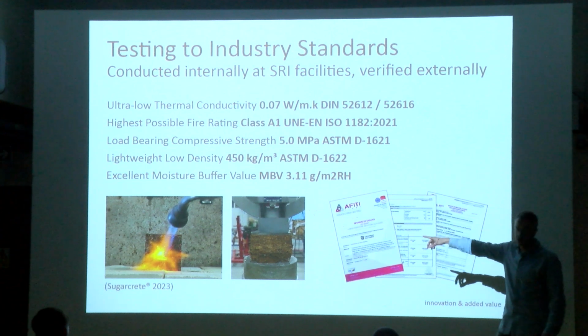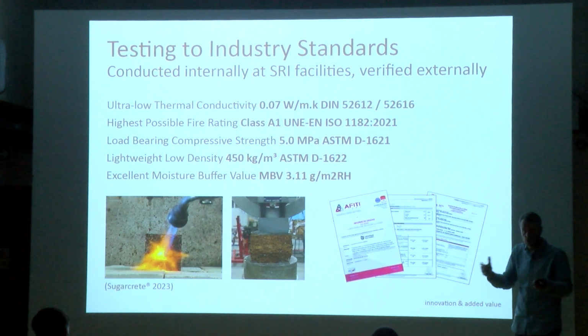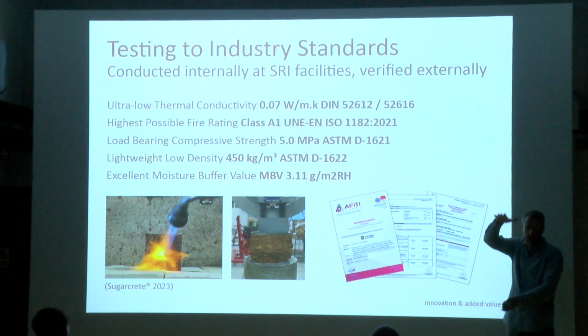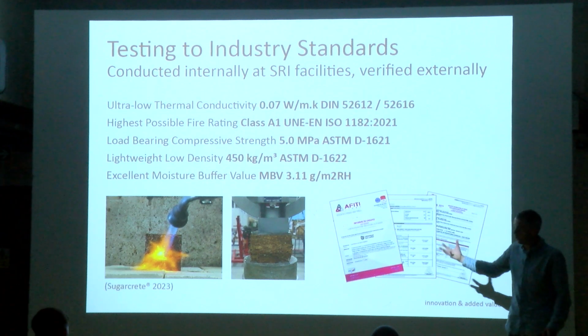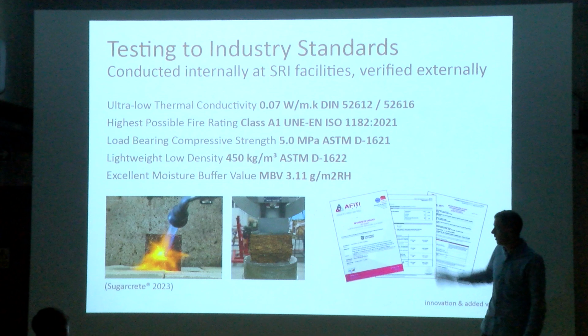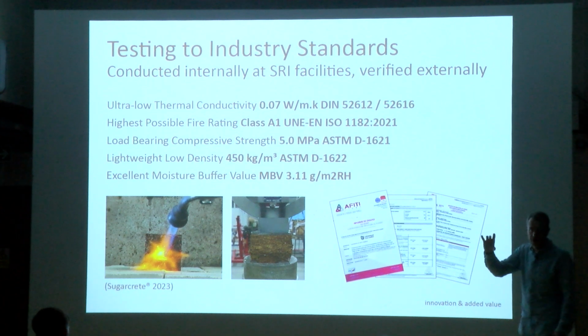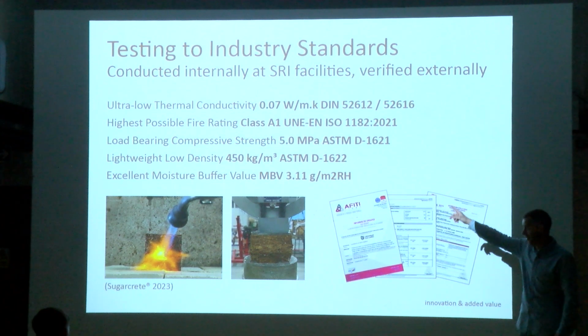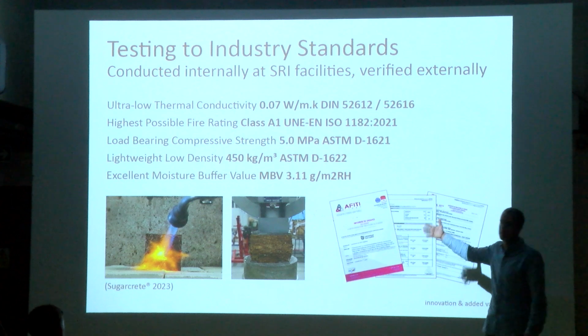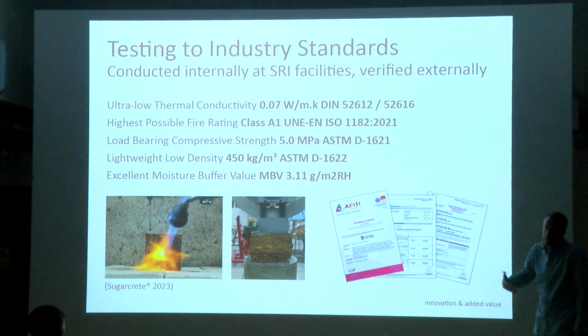However, the fibers of the biomaterials don't disappear, they don't go anywhere, they stay there, so you can continue applying pressure and there is still a lot of strength, almost 30% of strength that is left after the machine is detecting that the material is failing. So we could add that 30% to that number. We haven't, because the test is telling you that you cannot, but in theory you could.